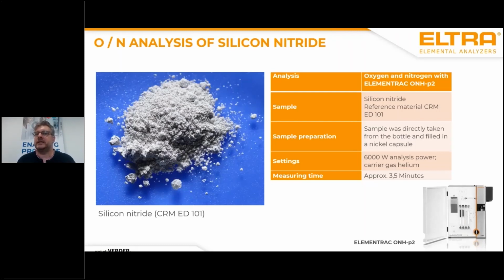And this silicon nitride sample, for example, was just taken from the bottle, and we applied a typical analysis power of 6,000 watt, and the analysis time is about 3.5 minutes for this kind of samples. On the left side, you see a sample. It's a fine disintegrated powder, but of course, it's also possible to process samples which are in solid shape or maybe have a different shape than a powder.